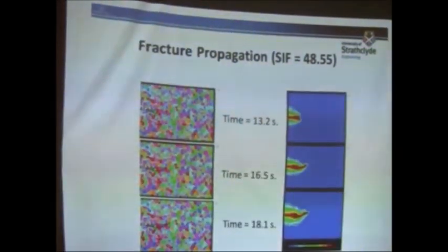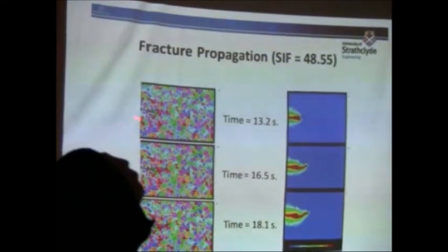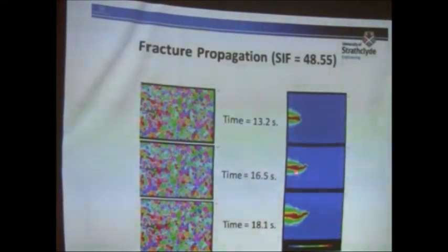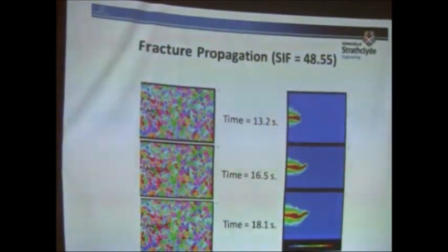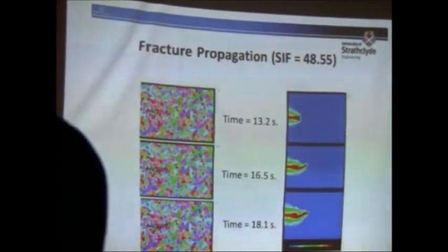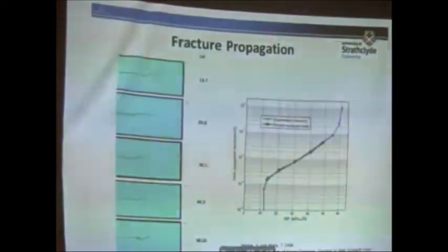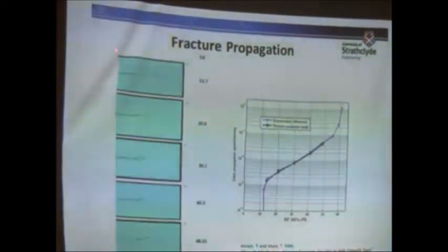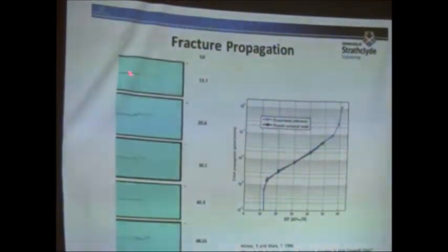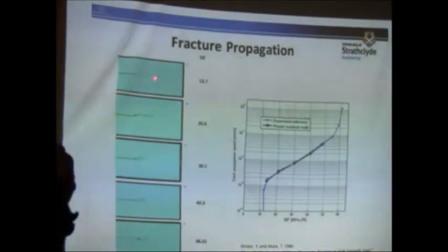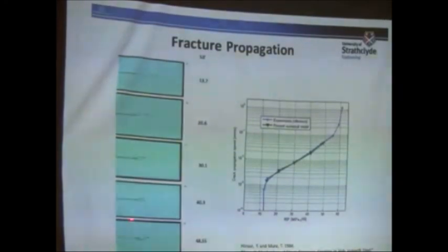Something that we need to pay attention to when you do this simulation is, once the crack starts to propagate, you need to update the boundary condition of your corrosive domain. Because now you have new crack surfaces, corrosive fluid should be pumped inside of this crack. So you need to keep updating your boundary conditions. These are some fracture patterns for different loading conditions. What we observed is, in some cases, the crack propagates following a single crack pattern, but in some other cases, we see this branching type of behavior, something that was observed in experiments.